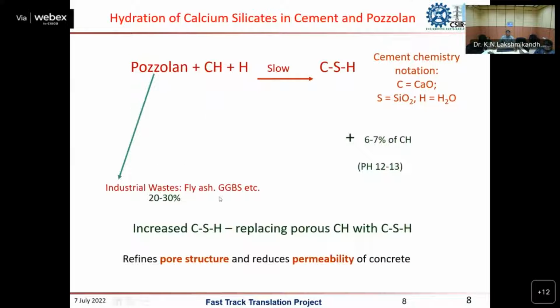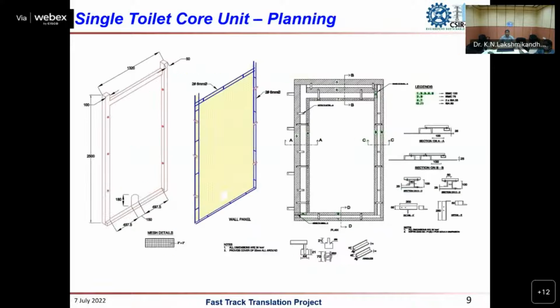Here what we are doing is replacing cement with pozzolanic material like fly ash or GGBS, which is industrial waste from industries. This will react with the calcium hydroxide and form more CSH gel. This way we can effectively utilize this waste material for producing a better concreting material. When the calcium hydroxide is converted to CSH gel, it becomes a non-permeable concrete system. So this way we resist water, moisture or air entering the concrete medium, which gives better durability.